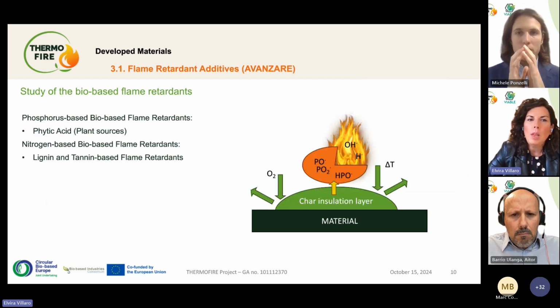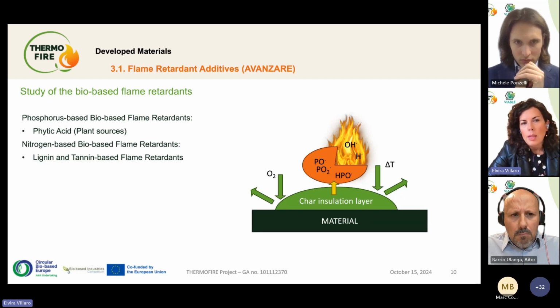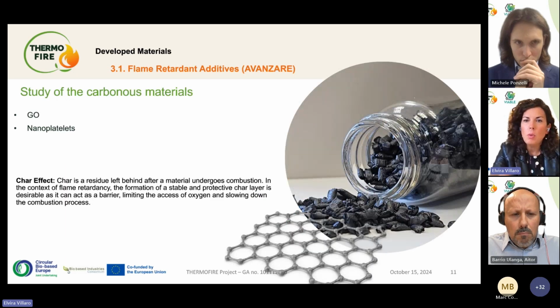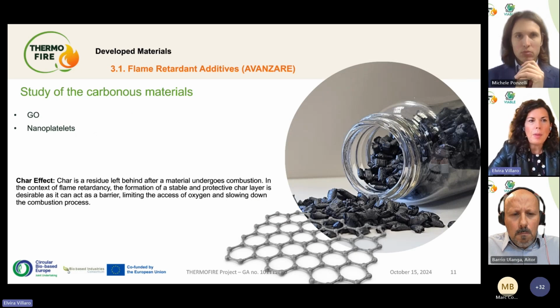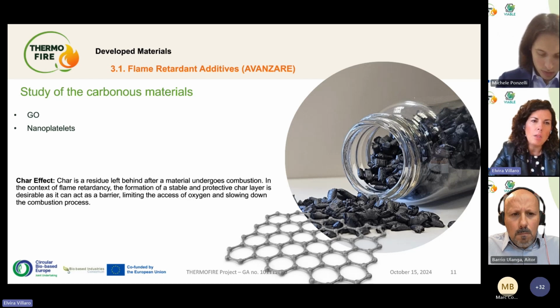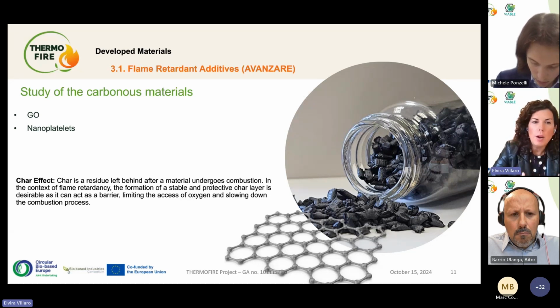If we focus on some of them that we obtain from plants, we are using phytic acid, lignin, and some tannins as flame retardants. But we are combining all of these flame retardants with other carbon materials that we are producing in-house. Avanzare is producing different types of carbon materials, which are graphene oxide and nanoplatelets. You can find in the bibliography that the combination of these carbon materials with some of the bio-based ones we mentioned creates a good, stable char, which is a layer helping us to reduce the combustion.